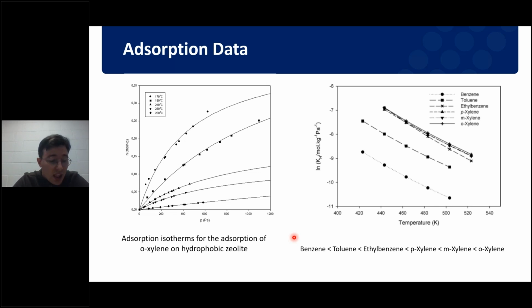And on the right here, we can see the sorption coefficients of various alkyl aromatics as a function of temperature. This demonstrates a qualitative difference in sorption affinity. As the molecular mass of our molecules gets larger, the Henry's adsorption coefficient gets larger and larger as well. The larger molecules, with that larger active surface area, that larger van der Waals area, exhibit the largest dispersive force, the larger uptake, and the larger energy of interaction.